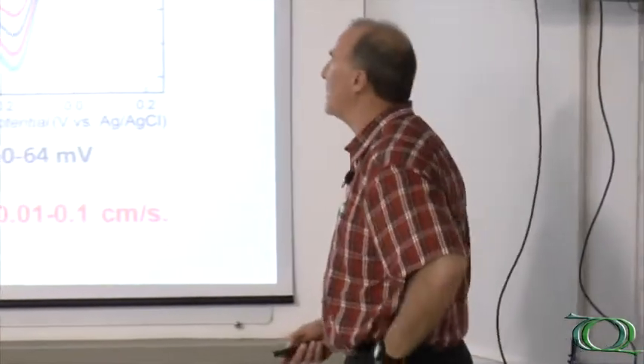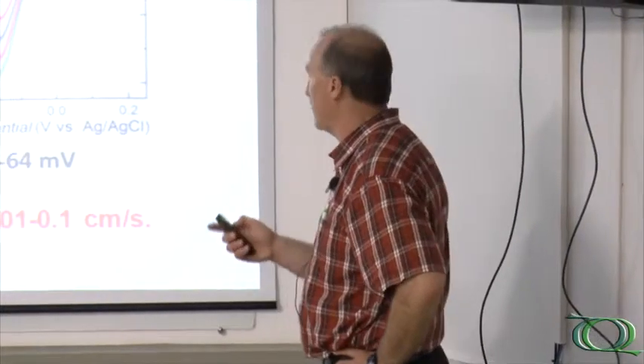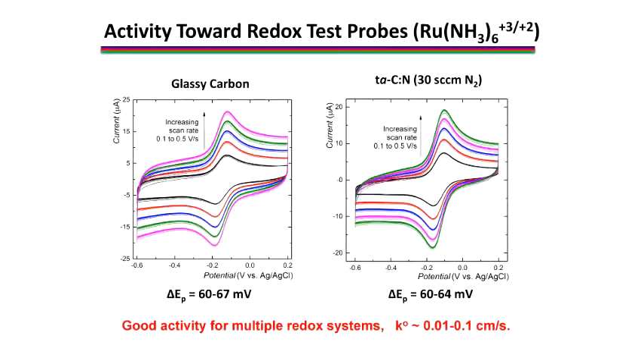We look at how things change with the scan rate and concentration and so forth. Here are some comparison voltammograms: glassy carbon on the left, tetrahedral amorphous carbon on the right. These are data from scan rates of 100 millivolts per second to 500. In both cases the waveforms evolve, very well defined. Importantly, the kinetics are pretty fast here. Even with the increase in scan rate, the system is almost Nernstian still, with very little change in the peak splitting for glassy carbon.